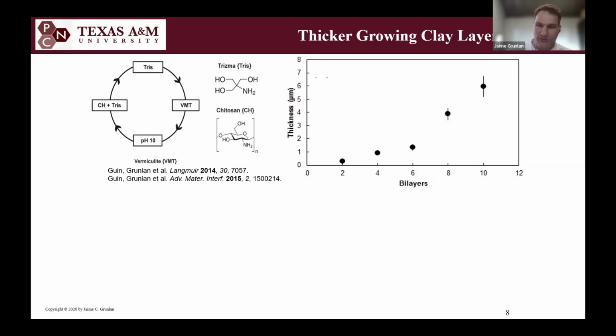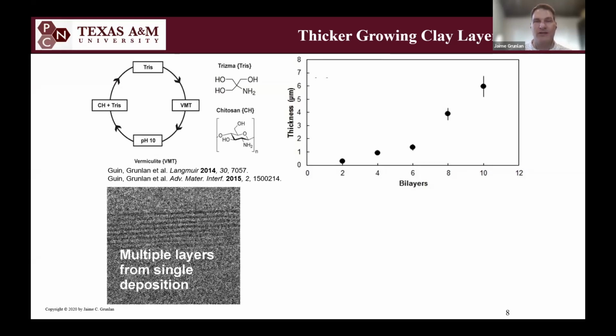You can play some games. I'm showing you immediately a trick we do to make thicker layers faster. In this case, I'm using chitosan as my cationic polymer, and I'm using vermiculite clay as my anionic nanoparticle or nanoplatelet. Vermiculite has a 2000 aspect ratio, a 1 nanometer thick plate that's on average 2000 nanometers in diameter. But when I put this Trizma base, or sometimes we just call it tris buffer, into my chitosan solution, and I also put it into my rinsing solutions, it causes a thickening of the clay as it deposits, because there's some kind of a complexation that happens as you're depositing the clay. And so now you can see 6 and 8 bilayers of growth are more than 4. At 8 bilayers, I'm more than 4 microns thick. So I've kind of engineered a little trick to get much thicker film much faster.